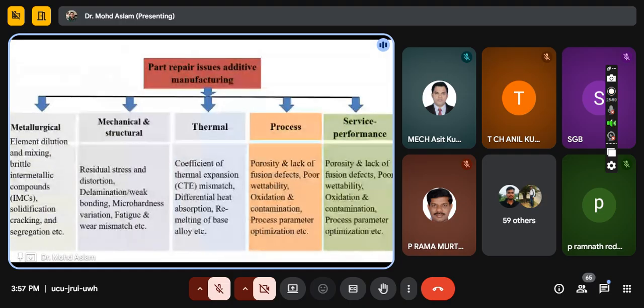And what are the thermal issues? Coefficient of thermal expansion mismatch, different heat absorption, and remelting of the base alloy. After that, what are the process issues? Porosities, lack of fusion defects, poor wettability, oxidation and contamination, and process parameter optimization. In the case of service performance, what are the issues? Porosity, lack of fusion defects, poor wettability, oxidation and contamination, process parameter optimization.